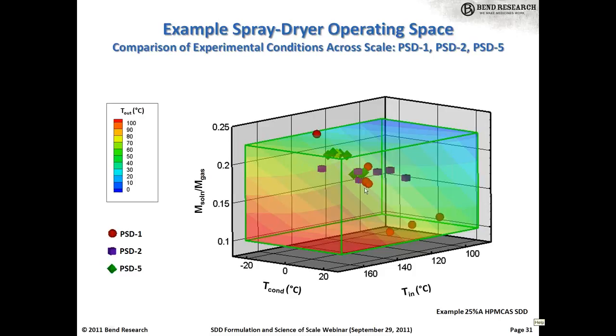And you can see for a very wide range of spray dryer scales, we can operate at similar thermodynamic conditions. In this particular case, we span everywhere from kind of on a PSD1 around a 20 kg per hour spray drying solution feed rate, all the way through to a 500 kg per hour spray solution feed rate. So it's a big difference in scales. Yet they can be operated at similar thermodynamic conditions.